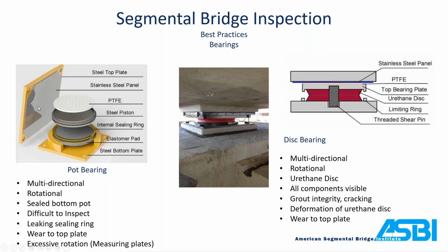And then we were getting some gouging on the steel plates that was causing the structure to bind up. So we swapped them out with these disc bearings, and you can see there's fewer components. Primary component is this urethane disc here. You have the stainless steel and the PTFE for your bond breaker and your sliding. And then you just have this threaded pin through the center, which you really can't see.